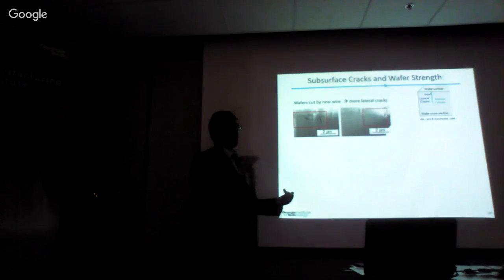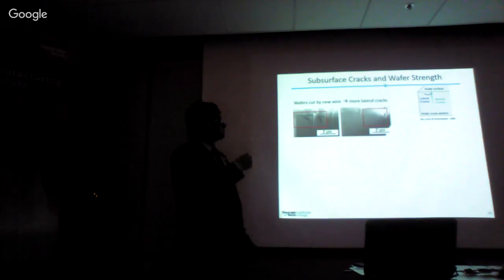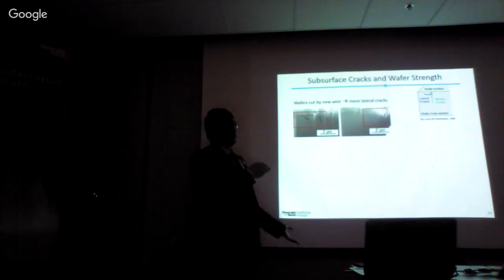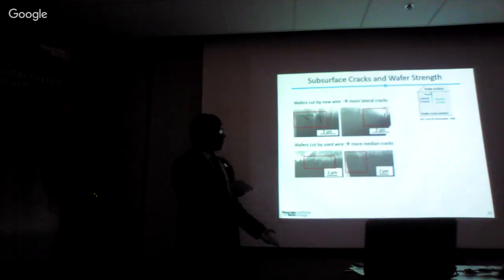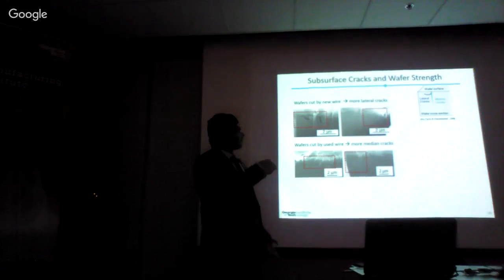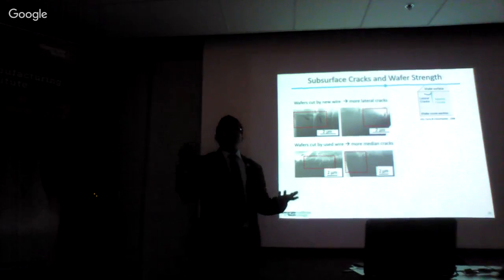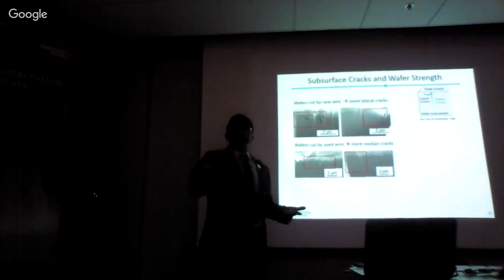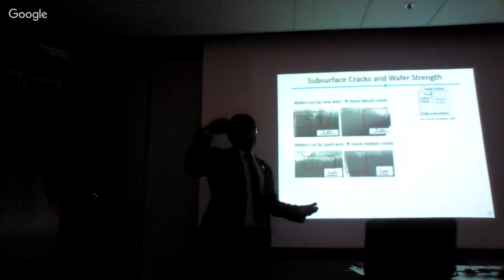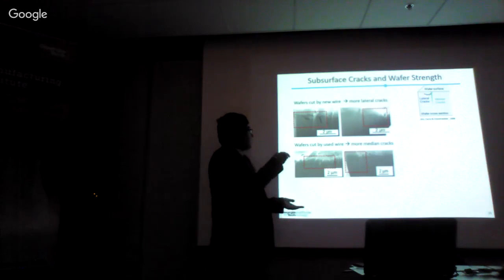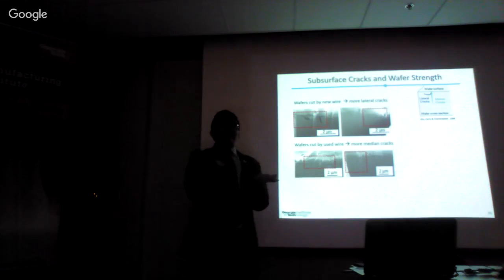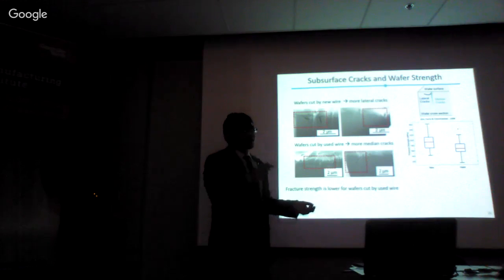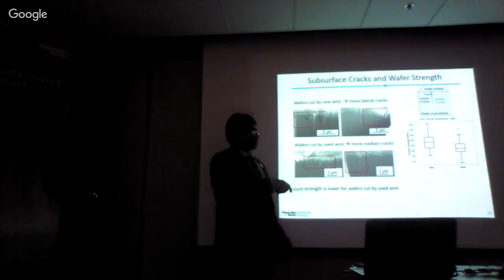Now, if you look at the subsurface of wafers cut by the new wire, we see there are some median cracks, but there are a lot more lateral cracks. And these are representative images of many, many sections investigated in the FIB. Compared to the wafers cut by the new wire, which showed more lateral cracks, the wafers cut by the used wire showed a lot more median cracks and not the curling upward lateral cracks. The median cracks here are not perpendicular to the surface because the abrasives are not idealized-shaped indenters giving the load perpendicular. They are still median cracks, a little oblique, but they are deeper and are expected to cause fracture of the silicon wafers at a lower stress level. And that's what we find in the fracture strength results, which was done by biaxial fracture by our collaborators.